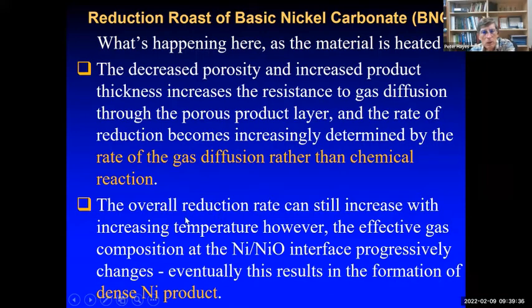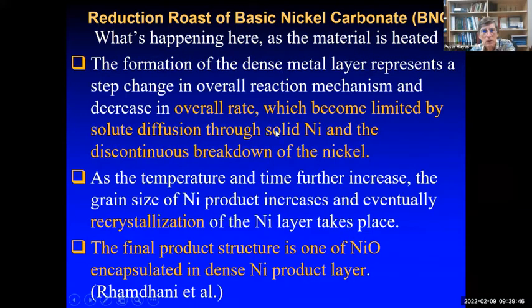and eventually we can get a situation where we no longer get a porous nickel reaction. We get the dense nickel. So it becomes limited by solid diffusion of oxygen through the nickel, and then we can only get reduction of the nickel oxide underneath by the discontinuous breakdown mechanism. And unfortunately, what happens then is we get the recrystallization of any remaining porous nickel, and we get the final encapsulation of the nickel oxide with dense nickel product. So increasing the temperature simply doesn't help us.